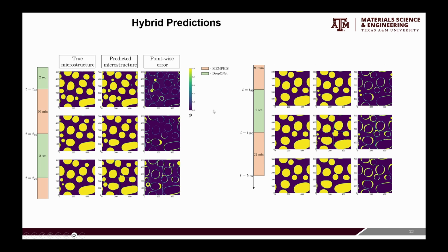And we can see now that the predicted microstructure is overcompensating for that small phase. We can see here in the true microstructure, that small phase disappears. It's completely gone by this time step. However, the predicted microstructure is retaining it for another 2 time steps. And we can see that here in the error. We can even see here that it's over predicting those. So that's probably the biggest room for improvement with this model, is how do you tune in exactly how much weight you give to each section of the time dependency.